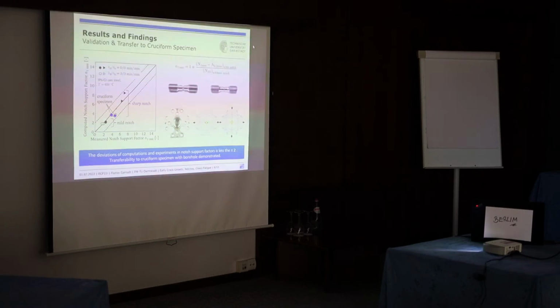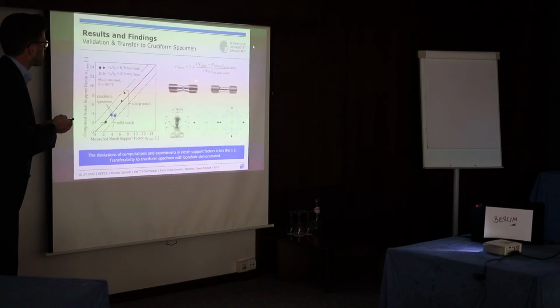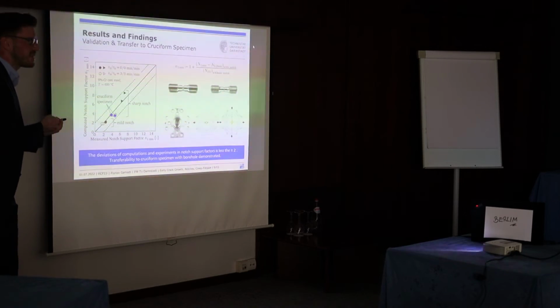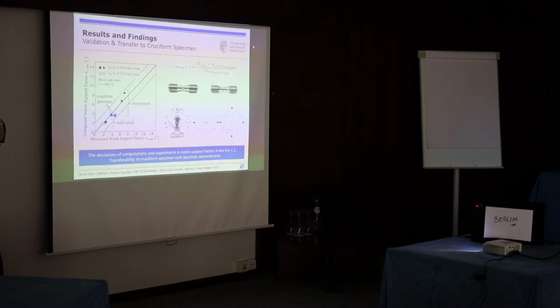I would like to show you here on this slide that we did some more tests, different loading levels, different geometries. You can see here by this plot where we plotted the computed over the measured notch support factor. Okay, short introduction of the notch support factor. It's just the ratio of cycle numbers for a notched and unnotched specimen. This is in the end what is interesting for the industry to have.